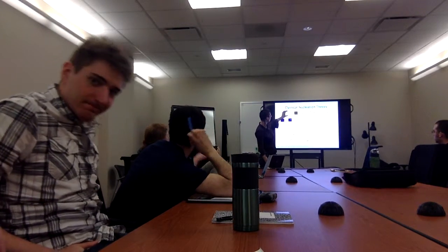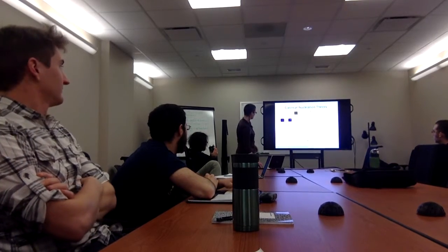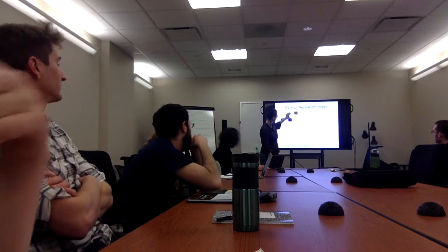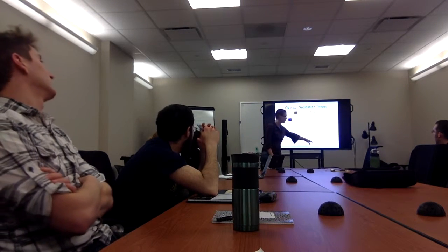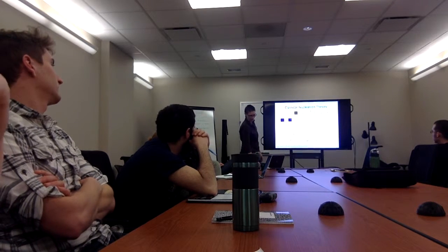So the probability of getting past this critical, so R squared would be the size of the radius of the nucleus at the point where it becomes more favorable for it to grow. And if all these assumptions are made, you can find the difference in free energy at this free energy barrier at the maximum point, and say that the probability of forming this nucleus is going to be an Arrhenius type function, so an exponential function of the free energy over the fluctuations in the system, whatever native fluctuations are happening in the fluid system you're starting with.